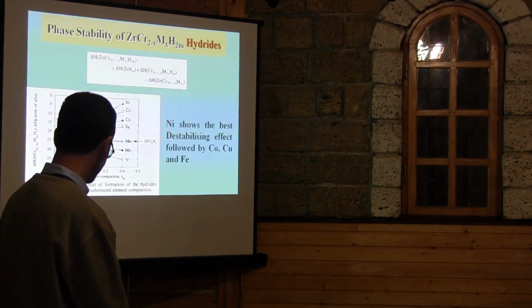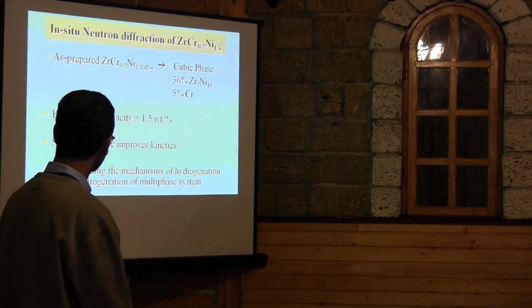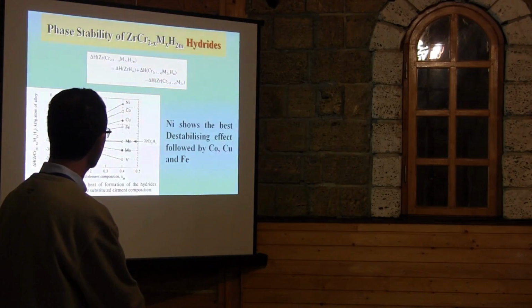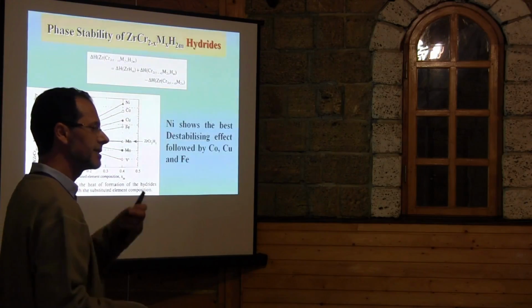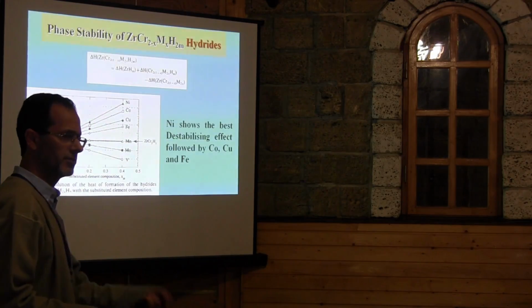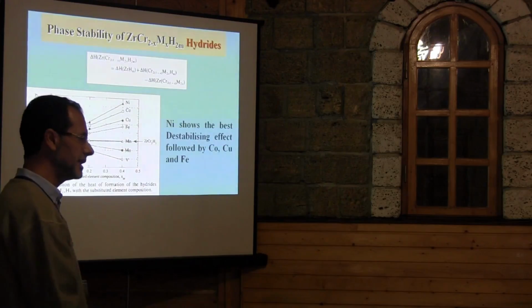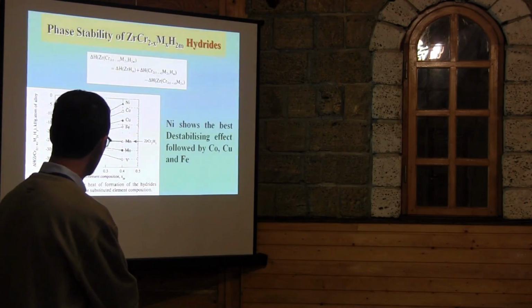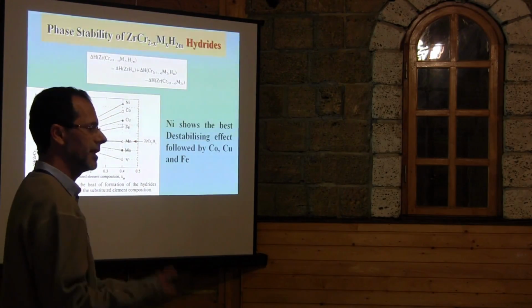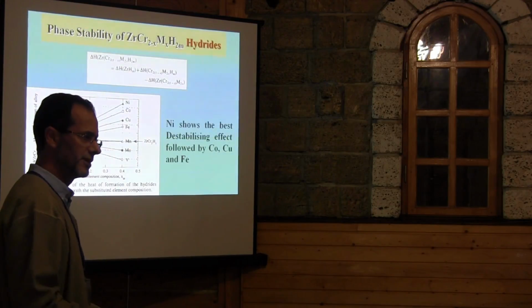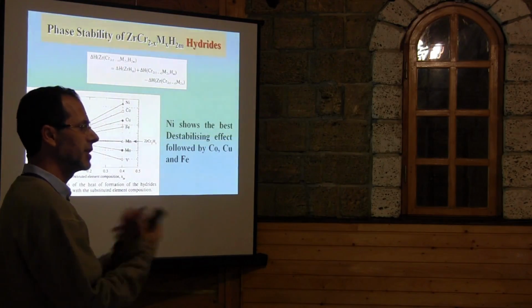So again, I find that these elements favor a less stable hydride. What does it mean, less stable? It means you can release hydrogen easily. If you put molybdenum and vanadium, they become more stable. That means you cannot release hydrogen. So this is very interesting because it's a prediction for me.